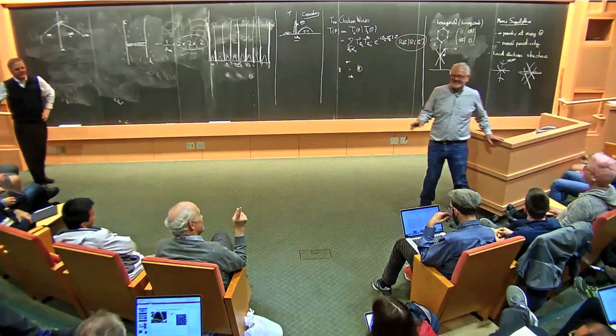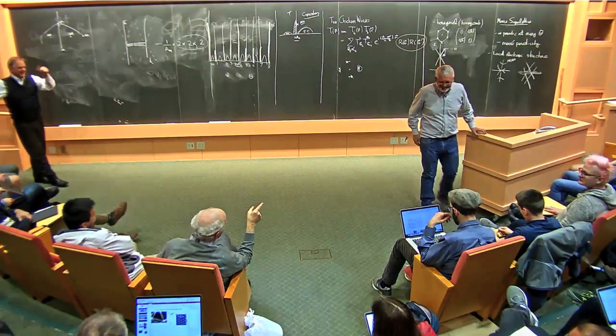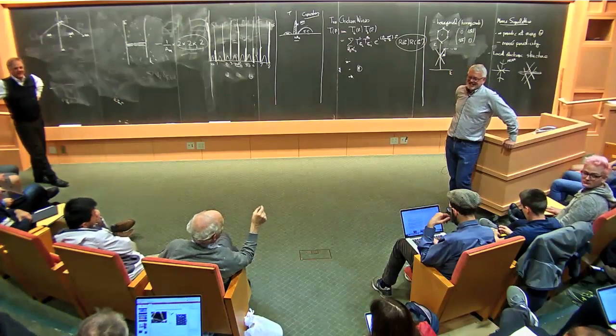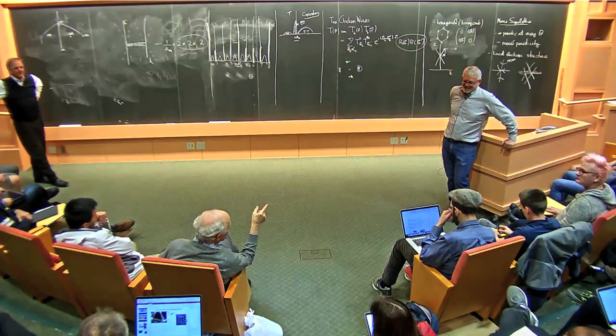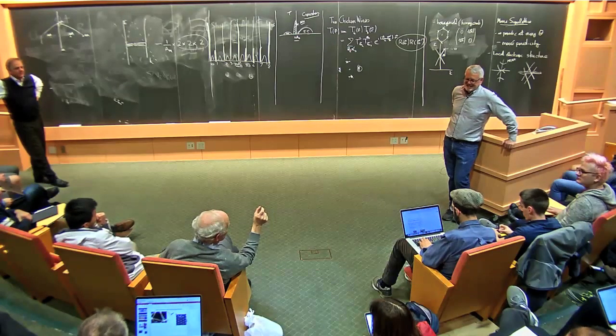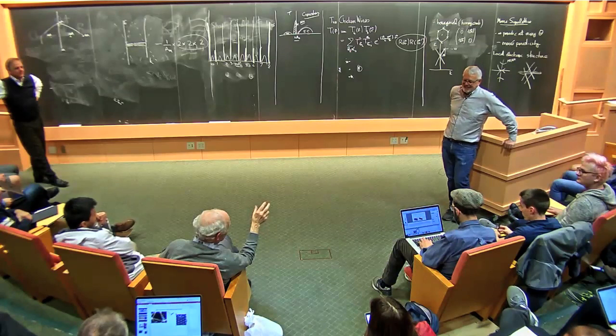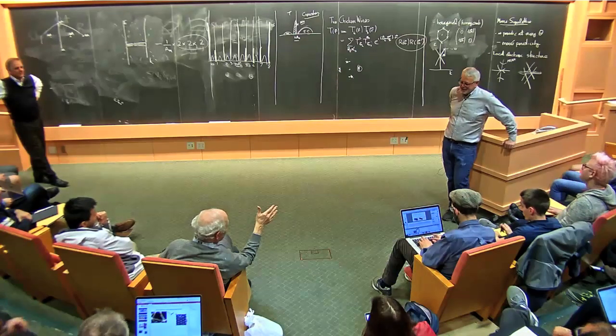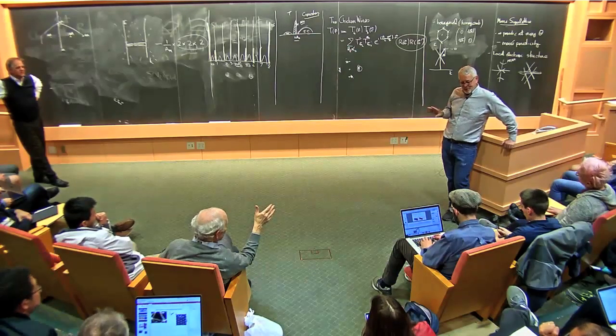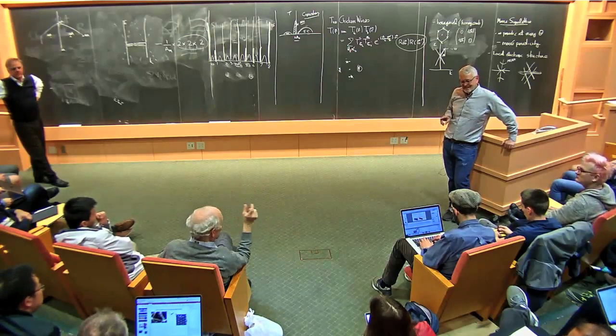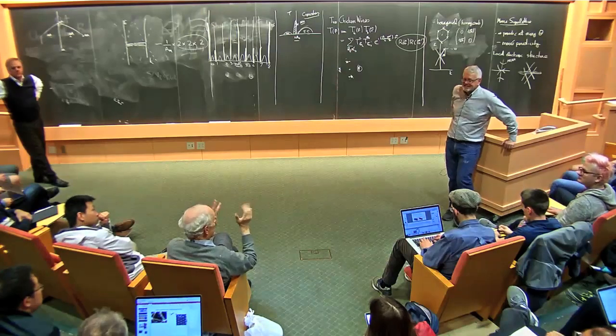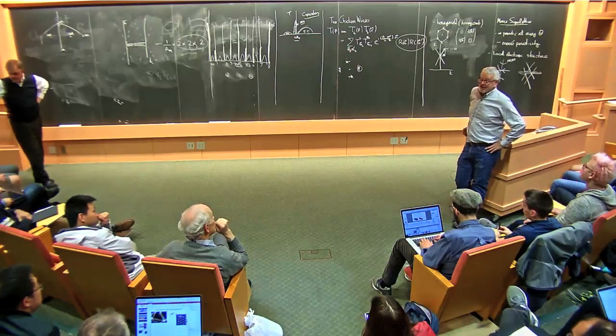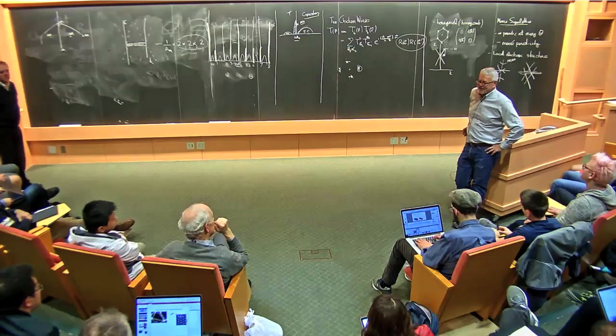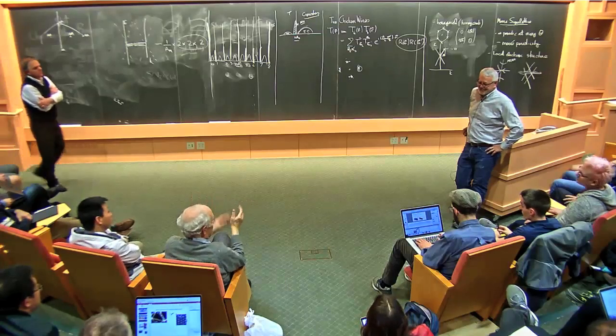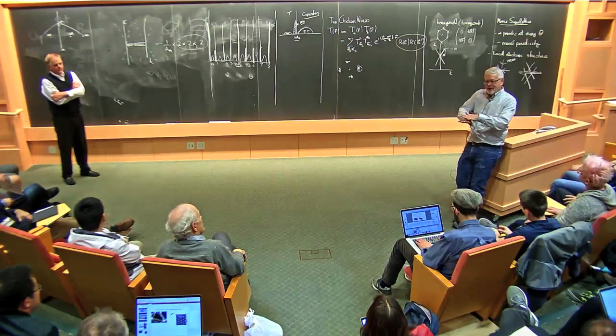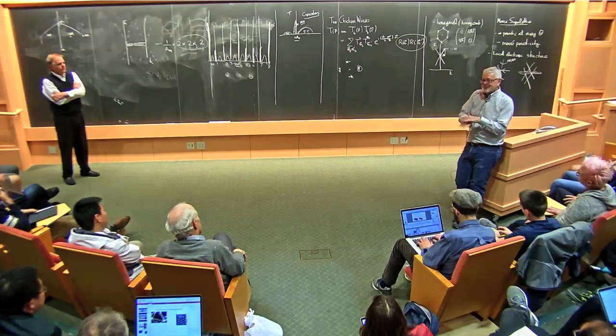Okay, Mark. In your discussion here, there's some small number, which is the distance between the lattice spacing and the theta. One thing that has to be small is treating the system as periodic. Your discussion was basically small theta and weak coupling between the layers. You can't do this with anything else. It's only van der Waals crystals where you can make these interesting superlattices just by twisting.